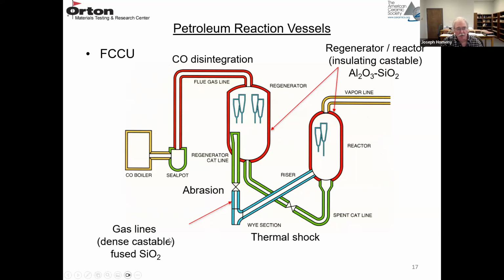So they're lined with a dense castable, usually a fused silica material, because as we learned, fused silica has low thermal expansion. So it's good in thermal shock resistance. It's also acidic. So if there's an acid-base process, it's resistant to acids. And if it's a reducing condition, CO disintegration may be an issue. Carbon monoxide attacks residual iron in the refractory and forms an iron carbide. And that volume change when the carbide is formed disintegrates the refractory.